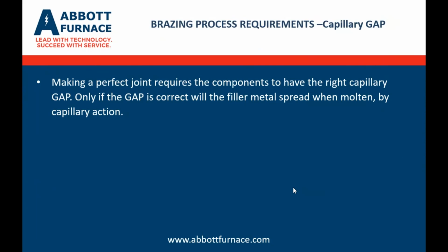The gap must allow molten flux to be drawn in to clean and dissolve the oxide layer. It must allow the filler metal to be drawn in freely and evenly into that gap, and the gap size will determine the capillary pull. Filler alloy, not in an excessive amount, must be available to fill the joint. And one of the sayings I've seen repeated several times over the years is filler metal can run, but it cannot jump. If the gap is too big, you're simply not going to get a full filled braze joint.